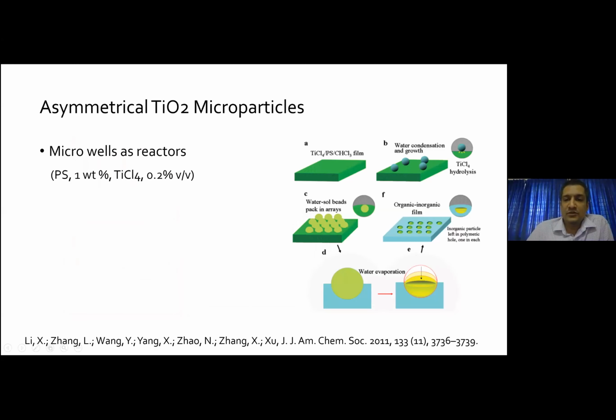To do chemistry on a very small scale is also very fascinating. Here are asymmetrical titanium dioxide microparticles. These asymmetric particles are of immense interest for physicists for various applications such as photonic band gap materials and so on. But preparation of these asymmetric particles is not so easy. This particular group tried to make the nanoparticle or microparticle inside the well by having precursors to the nanoparticles blended along with the polymer thin film you make.